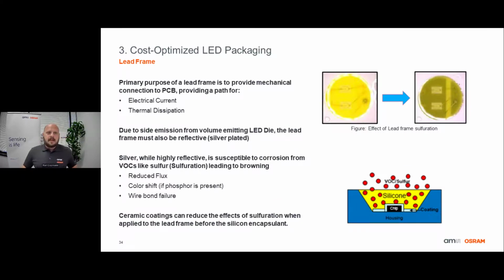Now, the primary purpose of the LED lead frame is to provide a reliable mechanical connection to the printed circuit board. This connection provides a path for electrical current as well as a path for thermal dissipation. The LED lead frame also contributes to the overall flux output, as those same photons that are being reflected off the inner surface of the LED housing may also come in contact with this lead frame. Now, in order to maximize reflectivity, the lead frame is often plated in silver. Silver is a highly reflective material. However, it is quite susceptible to corrosion from a variety of volatile organic compounds, or VOCs, especially sulfur.